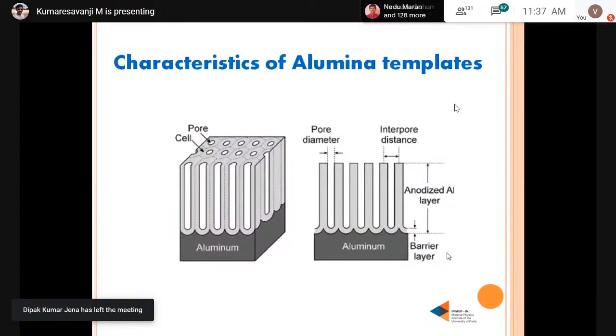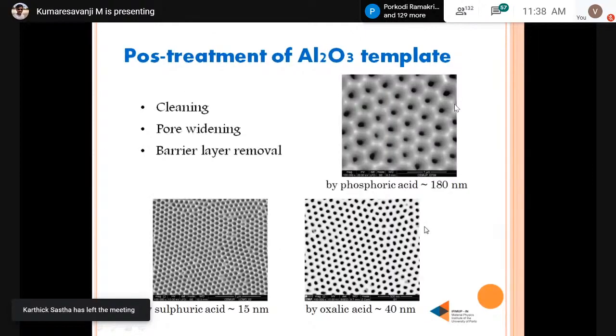So here I show how the nanoporous alumina template is obtained. We have the aluminum foil, the alumina barrier layer, the pore, the pore diameter and interpore distance, and this is the anodized alumina layer. After that, we have to clean it, because we have anodized it with different acids, right? So we have to clean it. Here I show some SEM micrographs of three different nanoporous alumina templates.